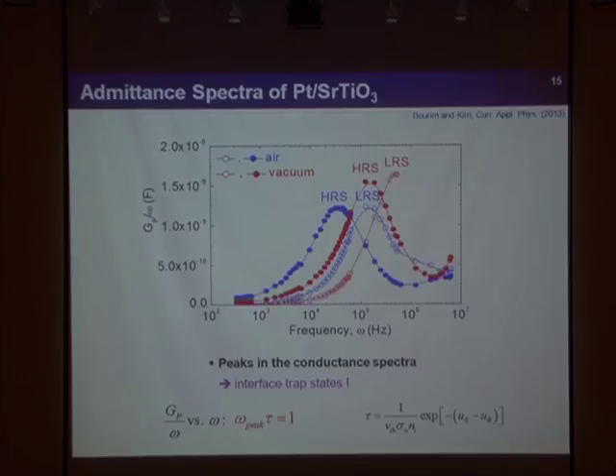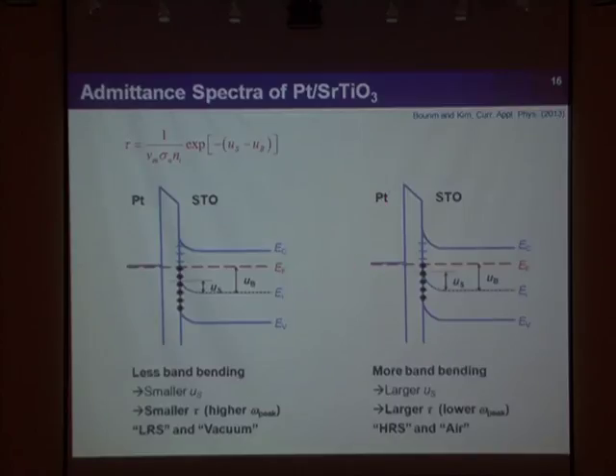What conclusion can be reached from this result? Basically this kind of picture is already known, however the detailed explanation is a bit different. To explain this change of surface band bending, we can say it's mainly due to the trap states. We don't have to invoke oxide vacancy migration.